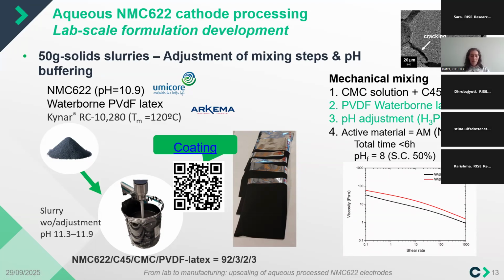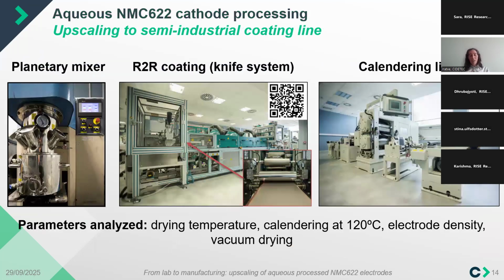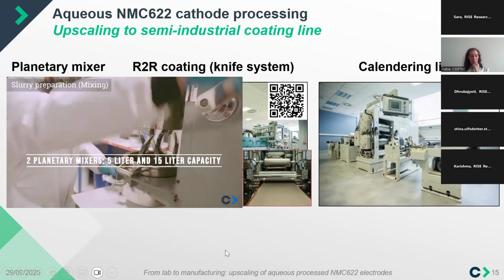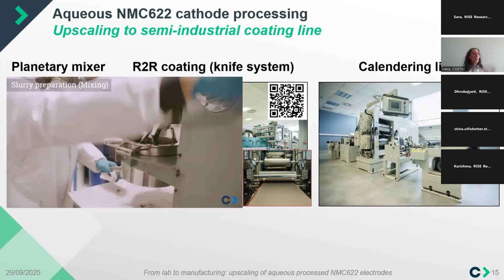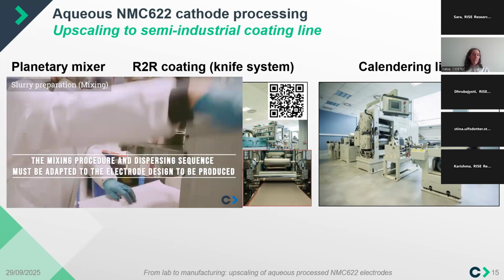Starting at the lab scale with 50 grams of solid slurries, the main challenge comes when you go from 50 grams, about 100 milliliters of slurry volume, up to coating lines—as seen here, at least 1 liter of slurry to coat in this continuous line of several meters length. I'll show some videos to illustrate this kind of upscaling.